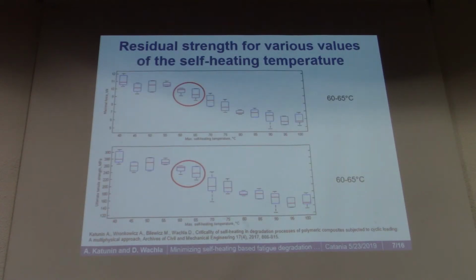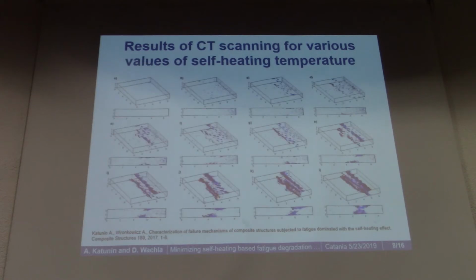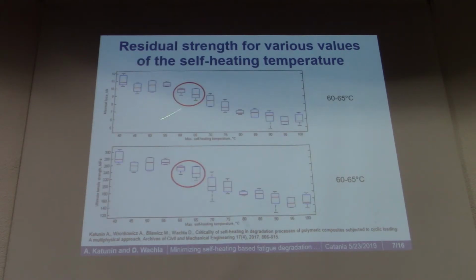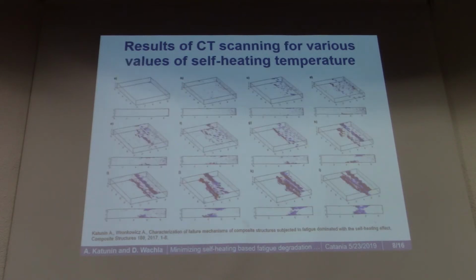We also did some static strength tests. We used specimens which were loaded up to obtaining a specific self-heating temperature, and then for these specimens we did quasi-static tensile tests. As you can see, this drop is also observable at similar temperatures.